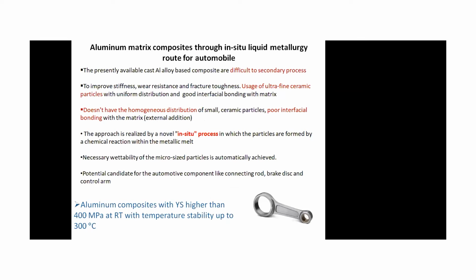Now come to the aluminum based composite. As I've told you, whenever you add any reinforcement into the system, when you deform any material, it is basically dislocation movement in the matrix, and metal is very susceptible to deformation, but ceramics are not susceptible to deformation because they are very hard. So if you add any ceramic particle into a matrix like aluminum or copper, secondary deformation is very difficult. Machining is also difficult. If you add ceramic in the form of very fine particles, like nano size or micron size particles, then it can be easily secondarily deformed. But if you add ceramic particles of maybe 100 micron or 50 micron, then it is also difficult to secondary process. Secondary deformation is nothing but rolling, forging, extrusion and other things.